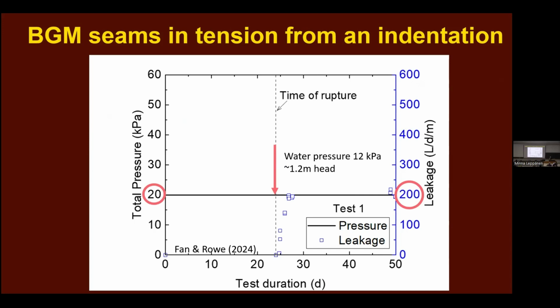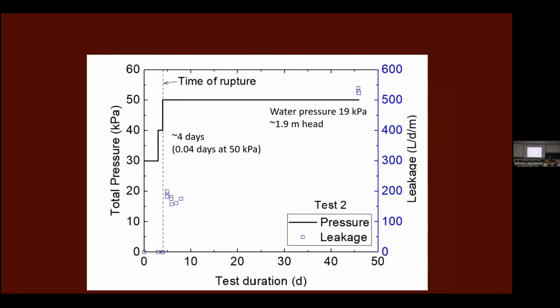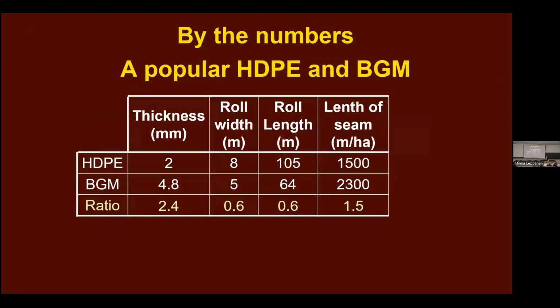And that's under a water pressure of 1.2 metres of head, 12 kilopascals. If I take it and load it to 30 kPa and then up to 50 kPa, it fails in 0.04 days at 50 kPa and 1.9 metres of head. And the leakage is 500 litres per day per metre. So let's look at the numbers.